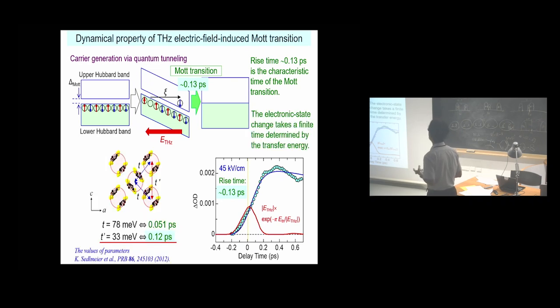It is reasonable to compare this time constant with the transfer energies. The interdimer transfer energies of this compound are shown here, and the smaller transfer energy, 33 meV, corresponds to 0.12 picosecond, which is comparable to this rise time. This suggests that the electronic state change in the Mott transition takes a finite time, determined by the transfer energy.